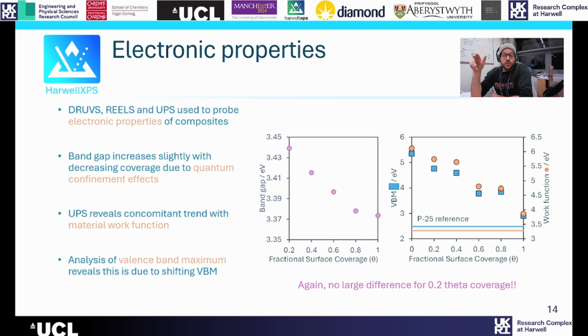So we do see a small increase in the band gap, which we ascribe to quantum confinement effects, when we go to smaller and smaller coverages. We also see a decrease in the valence band maximum and the work function, which suggests that core hole formation is getting slightly more favorable during the photoactivation of the more complete monolayer structure, so as we get to higher surface coverages. But again, all of this suggests slightly improved performance with increased coverages in a bit of a trend. And so this is kind of at odds with our catalytic observations, and realistically is unlikely to actually explain our results.